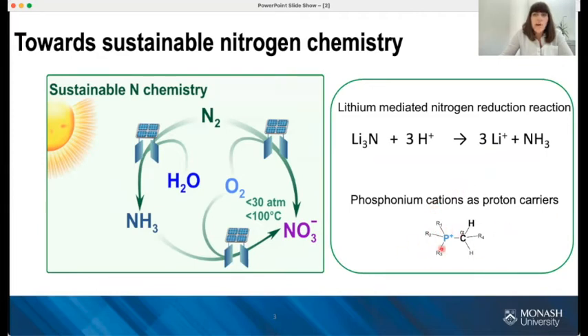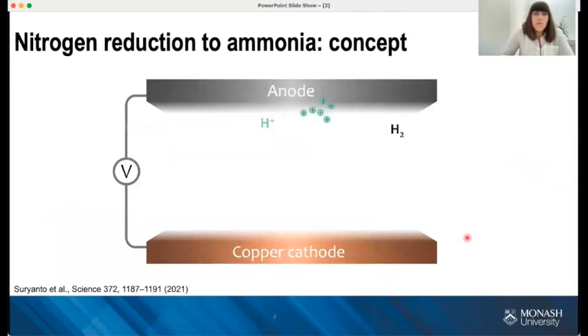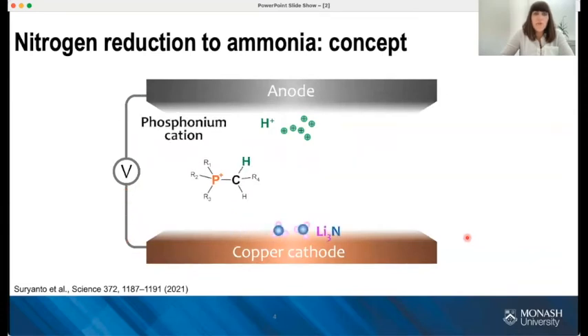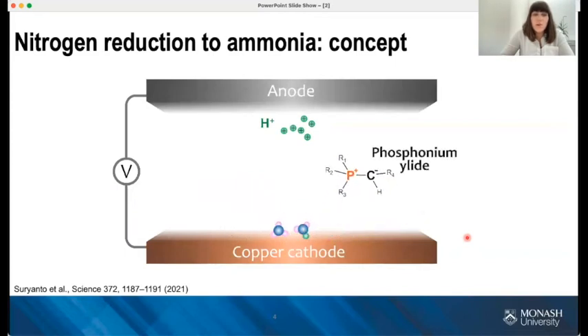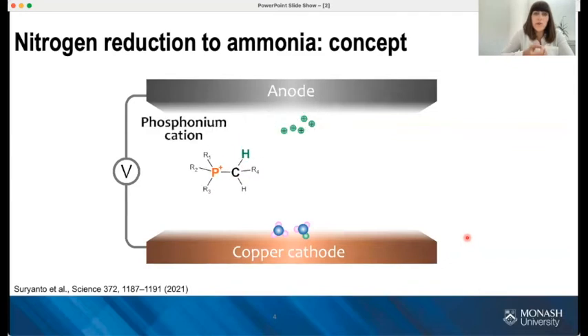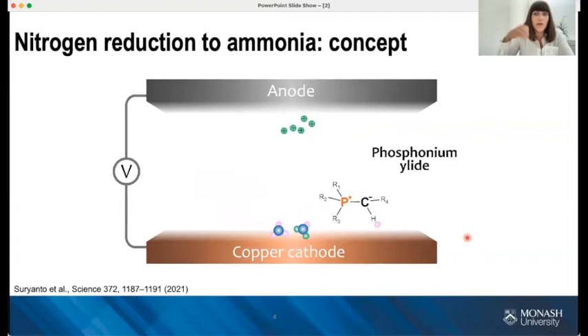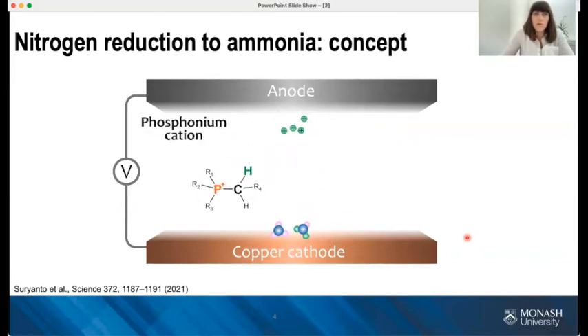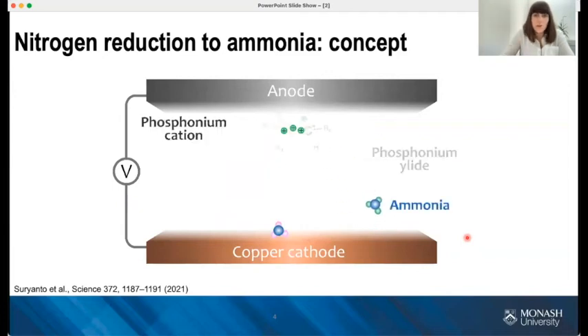Moreover, these structures are known in the literature for a long time for their reactivity. So the reactivity of those protons on the alpha carbon next to the phosphorus, which can be easily deprotonated. And the structure which is then formed is called an ylide, and it's commonly used in a Wittig reaction. So in our process, the reaction of the electrochemically generated lithium nitride with the phosphonium cation produces an ylide, that's it, and the ammonia molecule. The ylide compound is known to be a very strong base, so it gets reprotonated by the protons from the anodic oxidation reaction to regenerate the original phosphonium cation, and it can be cycled, as you can see here on the figure.